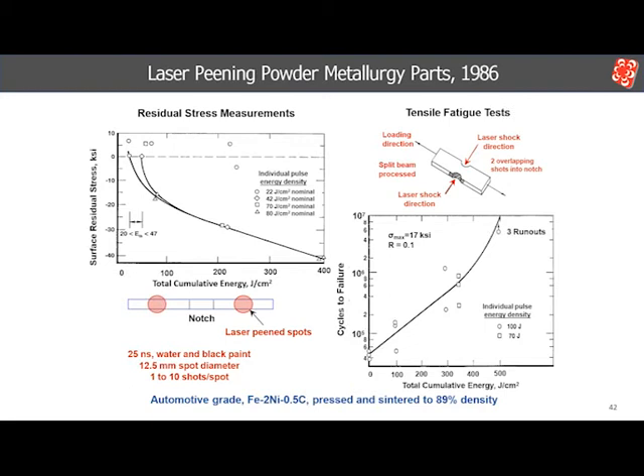They were a typical iron-powdered metal product consisting of pressed and sintered automotive-grade iron-nickel-carbon powder sintered to 89% density, so plenty of porosity. On the left is the surface compressive residual stress measured on one edge of the tensile specimens as shown in the drawing. The best fit to the data was with cumulative energy, that is, the sum of the energies of all the shots placed in one spot.